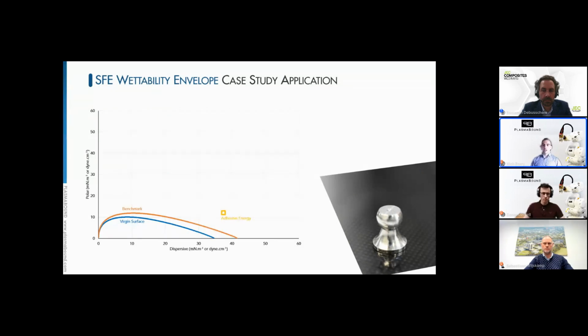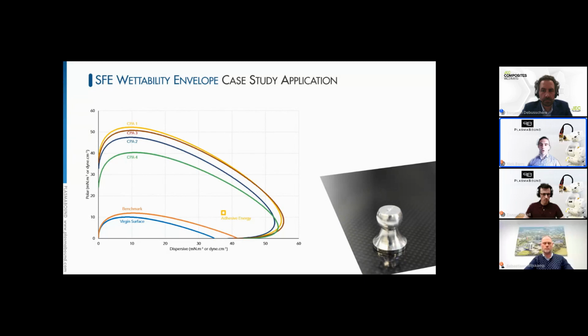During our trials, we created a series of CPA prepared surfaces, so first, second, third, and fourth, where we determined all four of these would be viable to create a bond or common interface with this adhesive, and we chose the CPA 4 to go forward to testing. The outcome of the mechanical testing was stark.